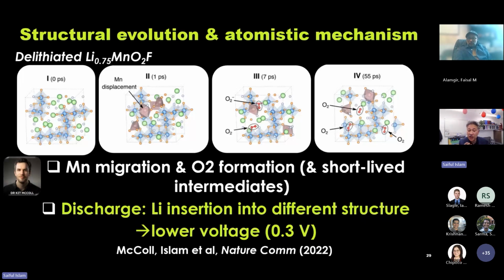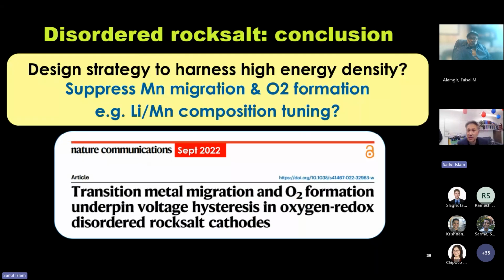And we published that a few years ago in Nature Comms on this disordered rock salt. So what is the take-home message here? The take-home message is similar. We need to suppress manganese migration and O2 formation if we want to harness high energy density lithium-rich disordered rock salts. And that has been done by people tuning the lithium manganese oxygen fluoride composition, actually to inhibit oxygen redox in these materials. And if you want more details, it's published in Nature Comms back in September 2022.